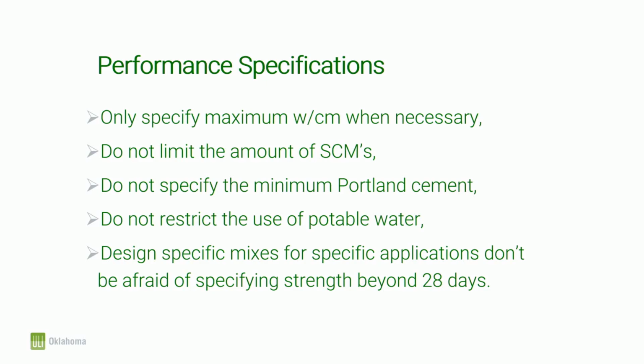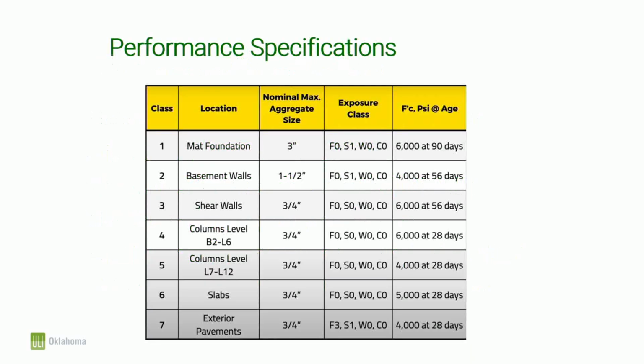So when you are doing your specifications, the idea right now is to move towards performance instead of prescriptive, so I can use the materials that I know about in the best possible way to reach the performance that you need in your building, your pavement, or anything you're building or specifying. One big thing that I tell everybody is that you can start designing per individual structural element, and you can move that PSI so we don't have to achieve everything with Portland cement. You let those supplementary cementitious materials, which have a secondary reaction, hydrate so we get the strength at not just 28 but 56 days and 90 days. If you're not going to use that structure at full occupancy for 6 months, you don't need that f'c in 28 days. We can wait, and concrete can maintain that strength gain for months to come.